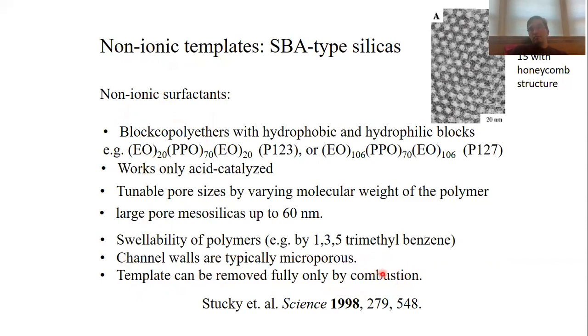The reason for that is, again, that the silica infiltrates the hydrophilic part of the micelle, and that traps some of the hydrophilic parts of the micelle within the silica pore walls. Therefore, by solvent extraction, you cannot remove the polymer fully from these silicas.